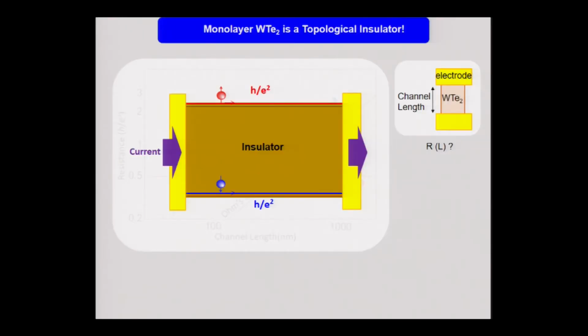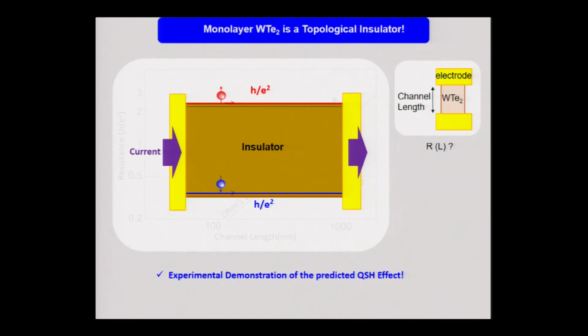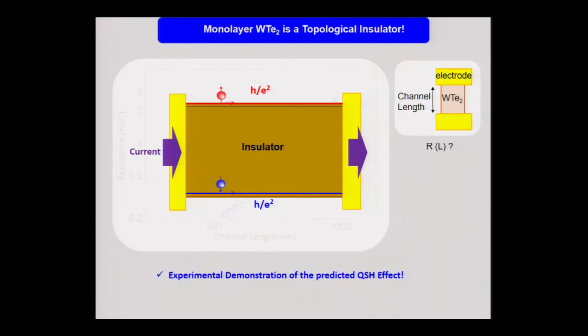And we also did a few other checks. The reason for this quantized conductance is that the interior of the material does not conduct, so current cannot flow there. If you put current into the material, it only flows along the edge. However, spin-up electrons only flow at the upper edge, and spin-down electrons only flow at the bottom edge, which means you essentially have only two quantum channels, which gives you e squared over h conductance per edge. This is the hallmark signature of quantum spin-Hall, and we also checked a few other necessary conditions, and we realized it's indeed the predicted effect for the quantum spin-Hall system in these materials.